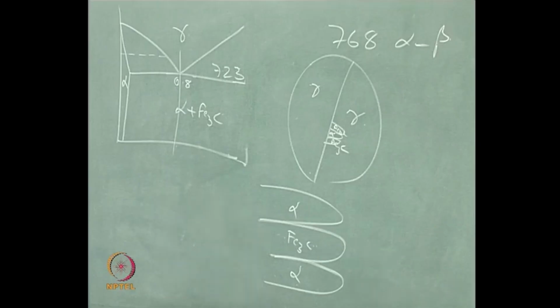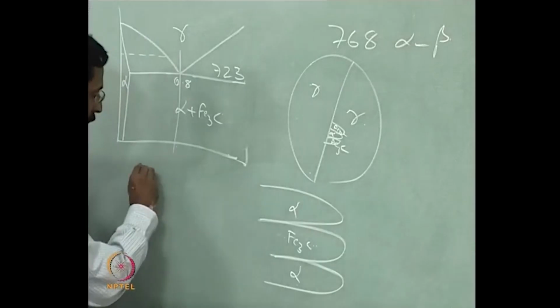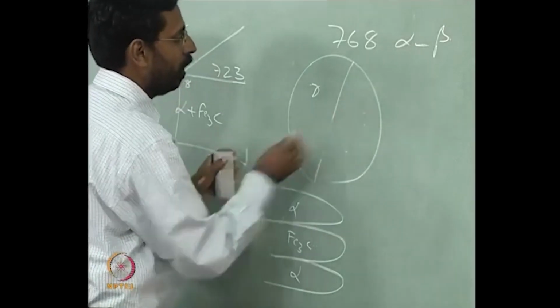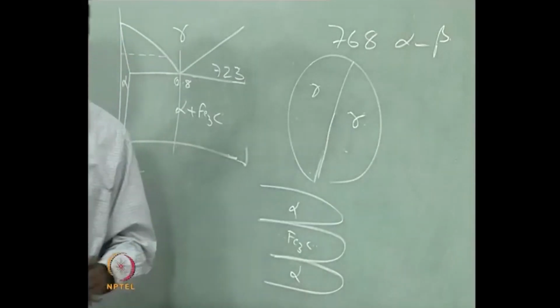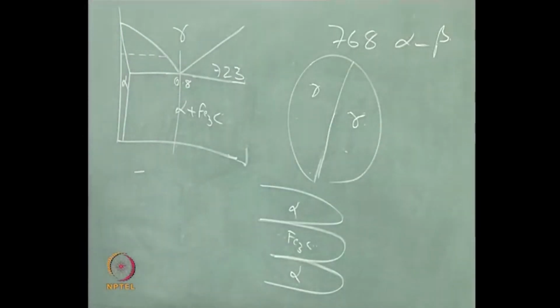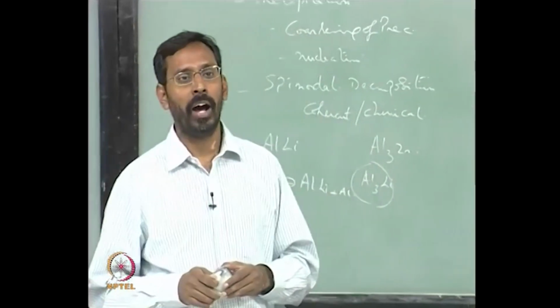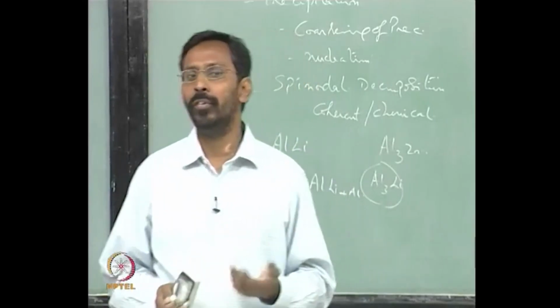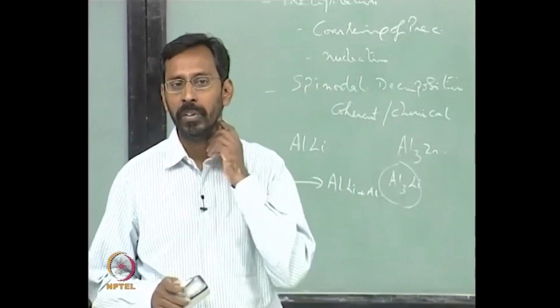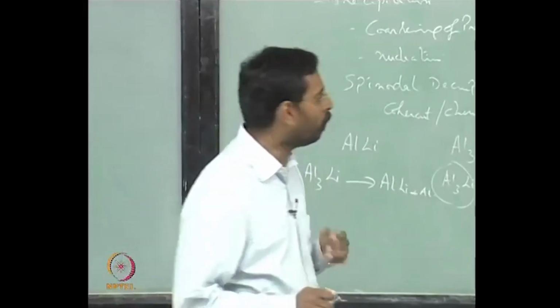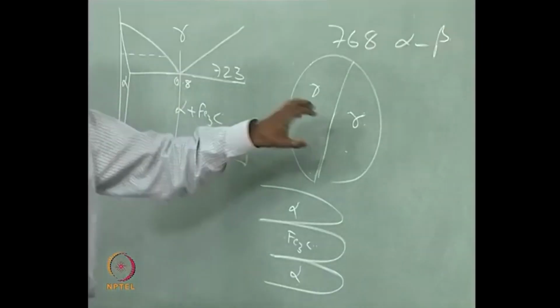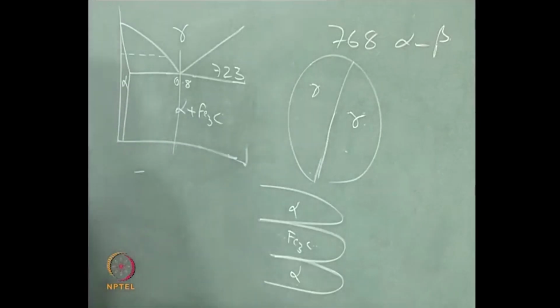after a lot of debate, what people have thought about is the moment I have, let us say, a situation like this: you have 2 gamma grains and you are keeping them at a temperature just below the eutectoid, which is around 723 degrees centigrade. What can diffuse more easily at that temperature? Carbon. Among the iron and carbon, carbon can diffuse very easily because it is an interstitial, smaller atom. So it can diffuse more easily, and as a result there is a possibility that at the grain boundary carbon atoms can accumulate.